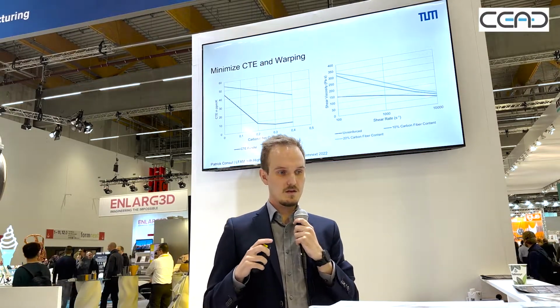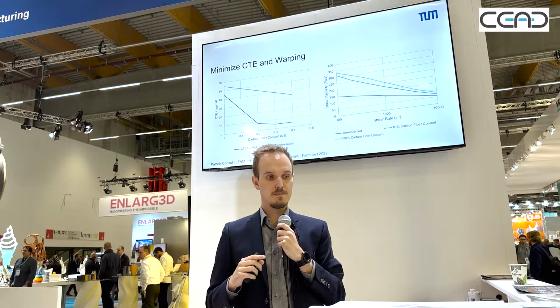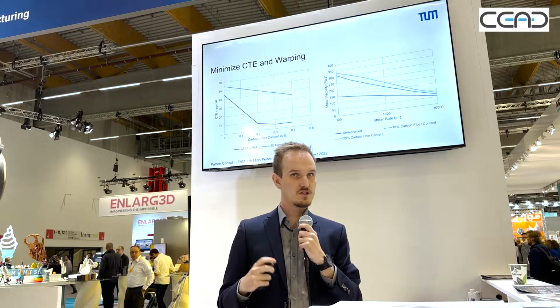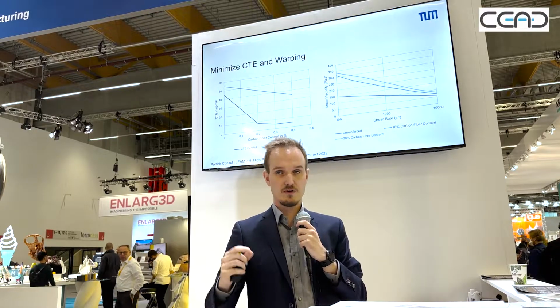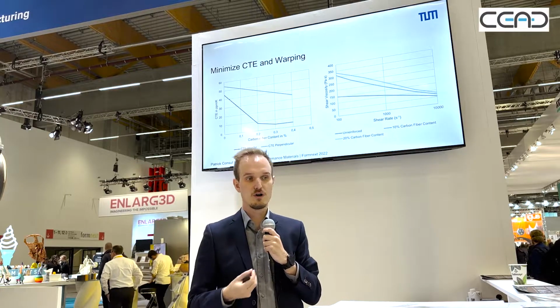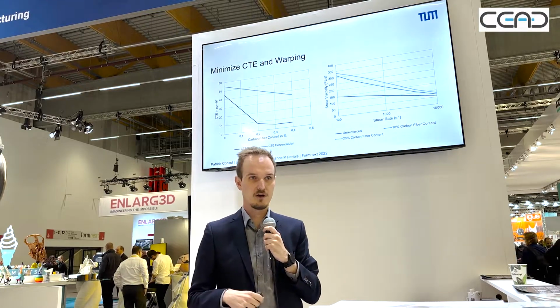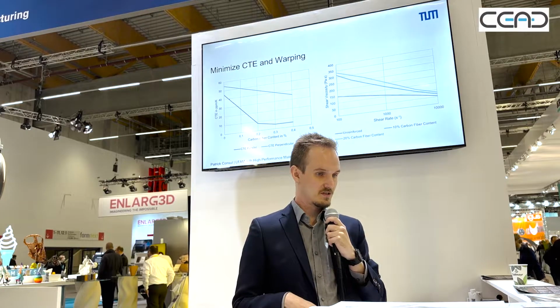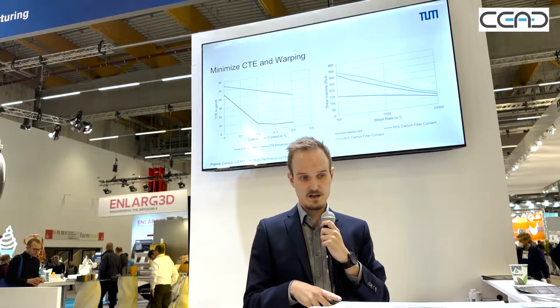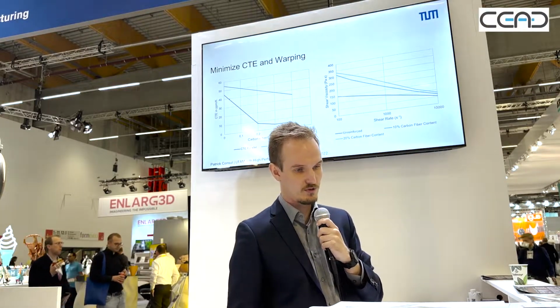And what's interesting to see is that by adding a little bit of carbon fiber, your viscosity drastically increases. But if you add more carbon fiber, the following increase is really not that high. So if you're going to add carbon fiber, you might as well go for it and add a lot of it, which will help you with the CTE and really push it down. We ended up going for one with 30% carbon fiber.